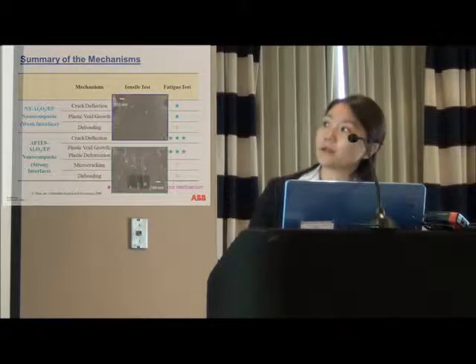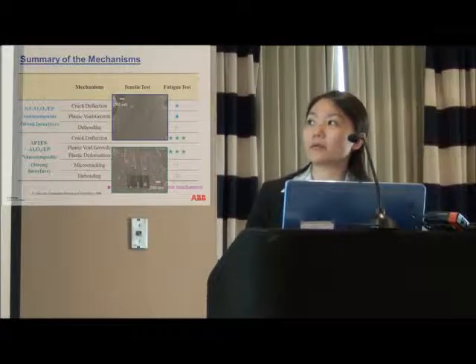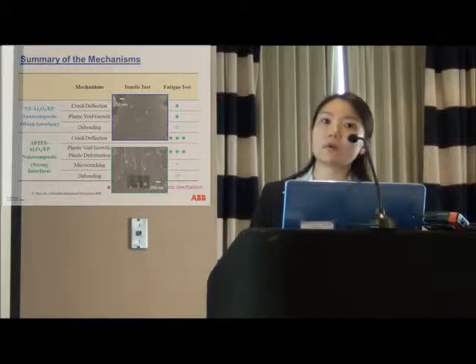For the non-treated one, this blue one, from my SEM picture you can see the crack is actually quite flat. When the crack reaches the particle, where you have a very weak interface, it just pulls out the particle and forms a hole, or goes above the particle, where you can see the spherical particle.